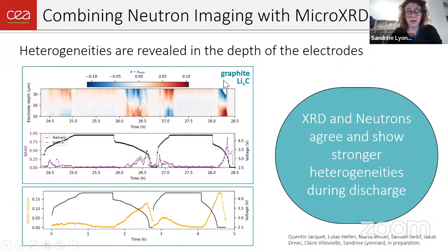This is exemplarily on the graphite electrode. What we measure is the state of lithiation of this graphite, which means the degree of lithiation, this X index. LixC6 are the phases that are formed. Maximum X is 1. And what we plot here on this map is the deviation of this degree with respect to the average value over the electrode. And this is the depth of the graphite electrode along the vertical axis. And this is time during the cycling. What you see is that you have some colors, some regions, which means you are having such strong heterogeneities that are developing in this electrode during the cycling of the battery.